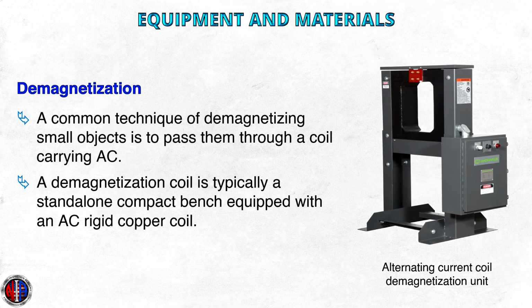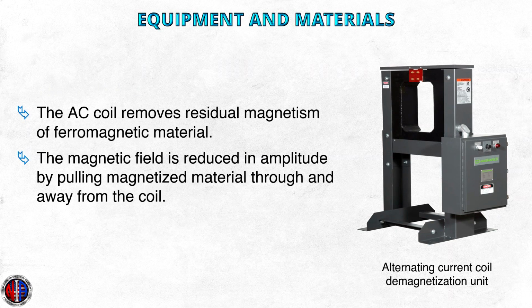Demagnetization. A common technique for demagnetizing small objects is to pass them through a coil carrying alternating current. A demagnetization coil is typically a standalone compact bench equipped with an AC rigid copper coil. The AC coil removes residual magnetism of ferromagnetic material after conducting a magnetic particle test. The operation is fairly straightforward with a simple on-off switch to manually pass the magnetized material through the coil. The magnetic field is reduced in amplitude by pulling magnetized material through and away from the coil. Due to the decaying alternating field, the magnetic domains inside the ferromagnetic material return to a random state.